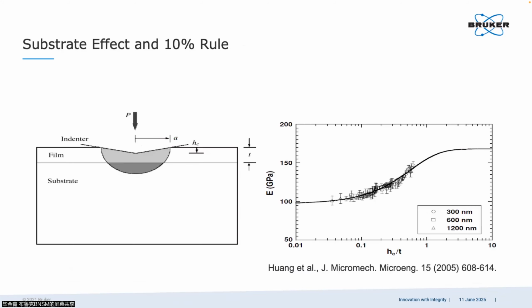Some researchers have studied the effect of the substrate from the viewpoint of film thickness. You will have what we call the normalized substrate effect. If you divide your indentation depth by the film thickness, you will find a very interesting behavior: all of these transition curves come together and are unified, no matter whether your film thickness is higher or lower. This is the source of the research for the rule of 10%, the so-called 10% rule. You can see this transition behavior.